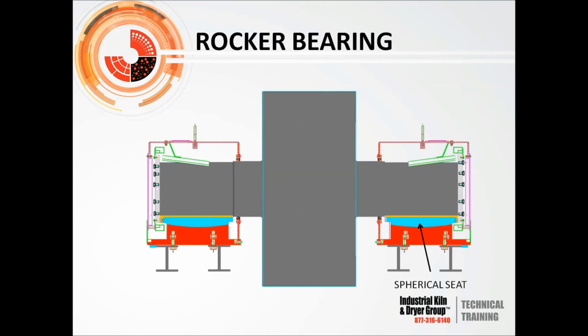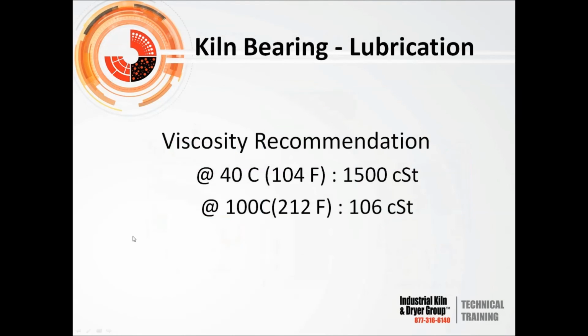Yeah, John, a lot of the other bearings aren't bolted down to the shaft. They just have a lug on the bottom, which goes up against the base to take the thrust load. And it's a little problematic to start shimming them because I've seen cases where they were over shimmed and that lug broke off and caused a problem. So you got to be careful about shimming bearings that are not bolted down. Yeah, and just one more point on that is that because there's no pivot in that bearing, if you try shimming on, for example, an Allis Chalmers style of bearing or a Fuller or something like that, you can run into some issues with the bearing liner not contacting correctly. So it's something you got to be very careful what you're doing.